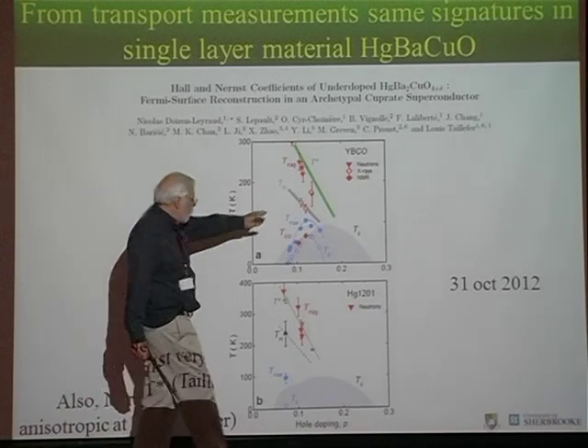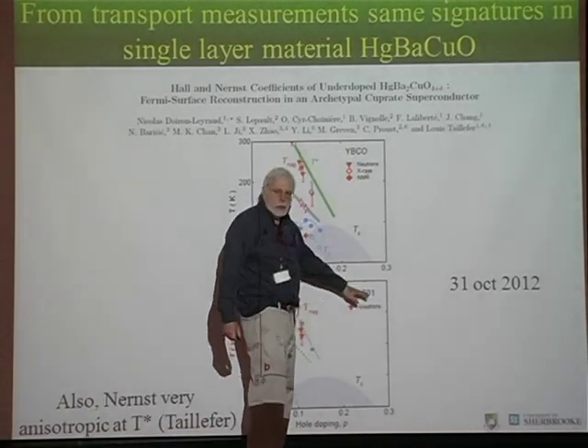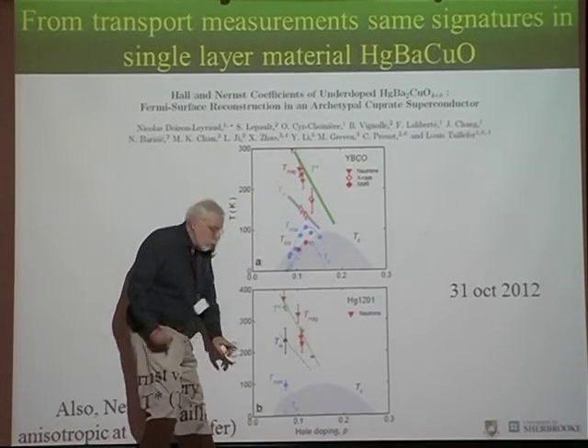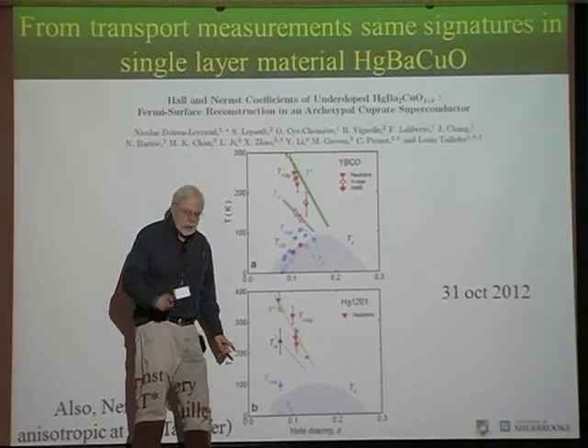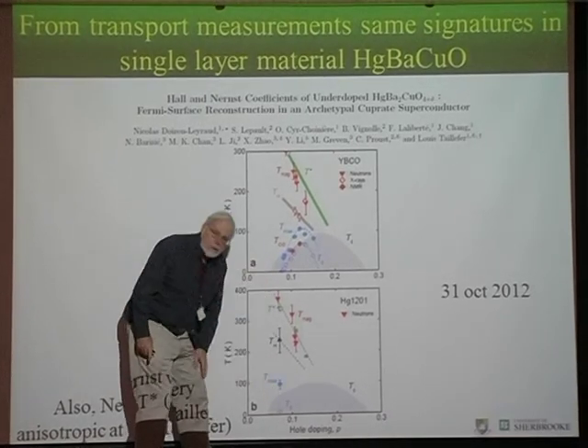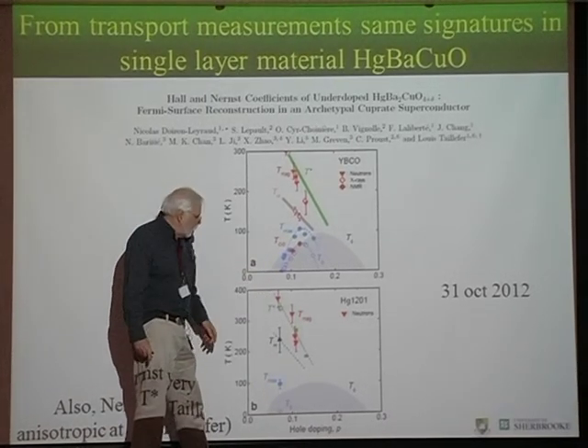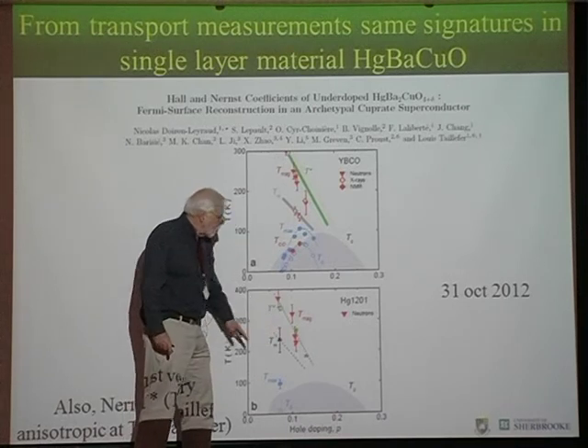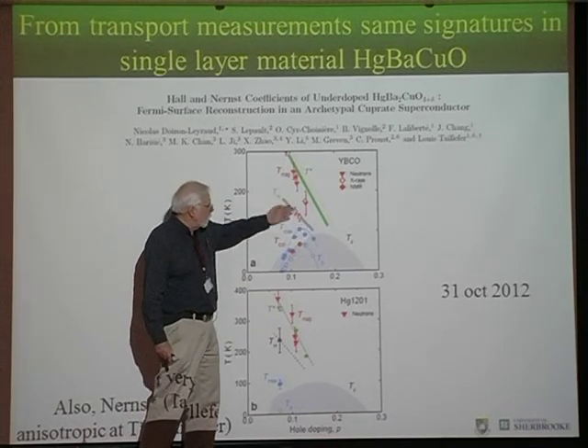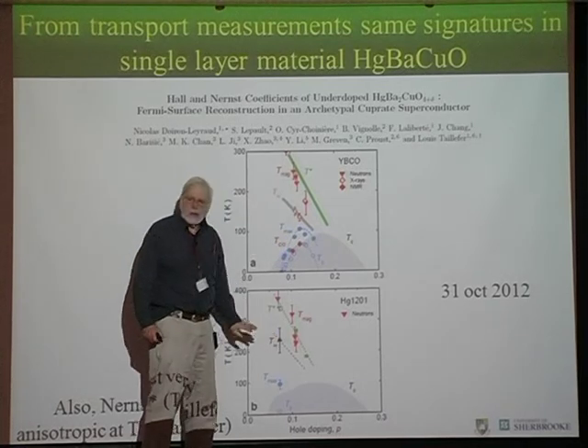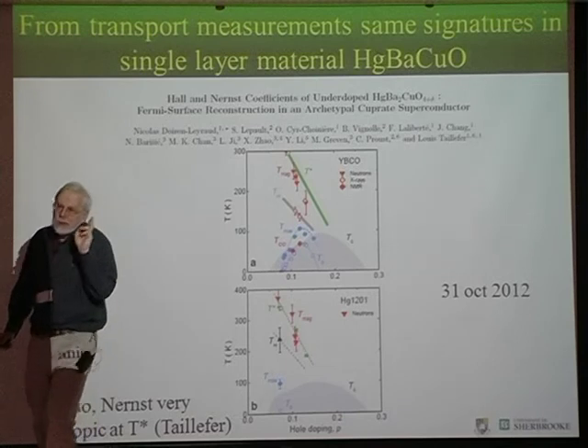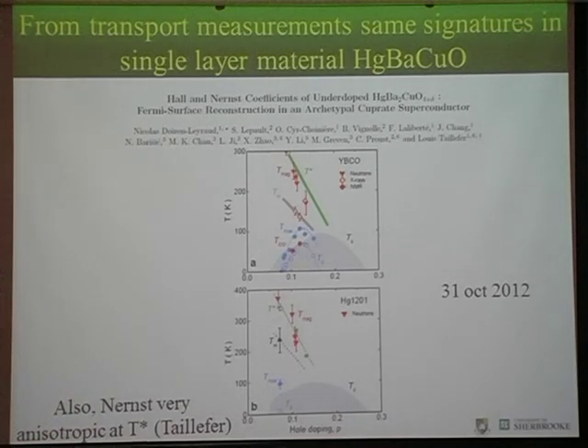Yeah, you see, this is YBCO, and this is mercury 1201. And even though it is a single layer compound, you see there's a small dip here. And if you look at the transport measurements, they're all the same signatures that Taillefer had seen here appear here. So it seems that at least in two compounds, there's this small dip, and it seems to be related to charge density waves. And the charge density waves don't seem to help superconductivity. They really compete.